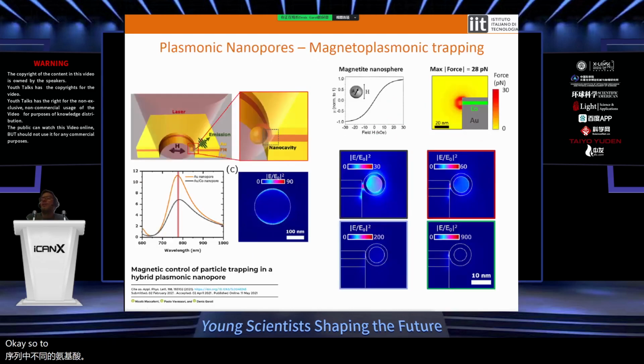Okay, so to conclude, now we are moving towards an alternative method where we want to replace the optical excitation used to trap the object inside the nanopore with an alternative stimulus, in this case generated by a magnetic field, moving from this pure plasmonic platform to a magnetoplasmonic platform. A magnetoplasmonic platform means that we can have both electromagnetic and pure magnetic properties. And as demonstrated here, we can trap our nanoparticle, and we can again generate this nanocavity where we can eventually perform enhanced spectroscopy, with a much higher force with respect to the force that you can obtain with just light, just using an external magnetic field. Okay, this is just to conclude, and thank you for your attention.